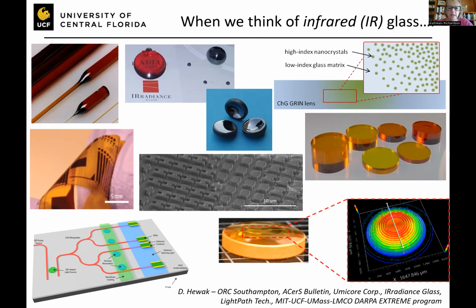One of the things that's interesting to understand is if we have a material that starts out glassy, we can convert it either to a glass ceramic. Depending on its composition, we can make the pattern structure that you see here in the middle where my cursor is. This is a lithographically produced thin film of optical phase change material that's based on many of the ingredients that we use to make glasses.